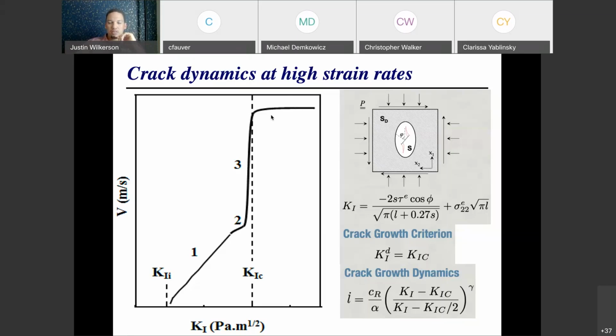And the reason that's important for the propagation of cracks is because there's some far field stress that needs to get concentrated at the tip of the crack, right? And the cracks themselves are free surfaces, so the Rayleigh wave speed becomes really important. Okay, the Rayleigh wave speed in most materials is going to be on the order of 1,000, 2,000, 3,000 meters per second, somewhere in that ballpark. So that's going to be the fastest that cracks can propagate through a material.